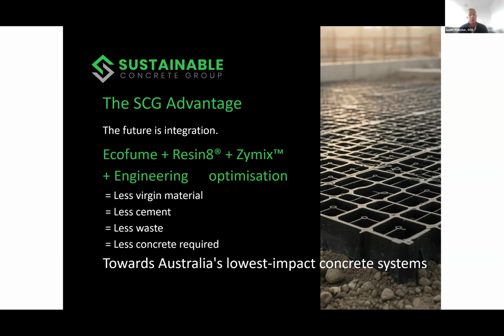We're able to use a matting where we will incorporate a mixed design incorporating the glass, the Resin8 product, with recycled plastic replacing 15 to 20% of the aggregate. That Resin8 can have aggregate size from 3 mil up to 20 mil, depending on the applications. And then with the Zymix with less cement, we are then able to use, for example, here, a matting that is 48 millimetres in thickness. We can cover that with approximately 20 to 30 millimetres of concrete over the top, and per square metre end up having quite literally a 10-tonne load capacity per square metre.